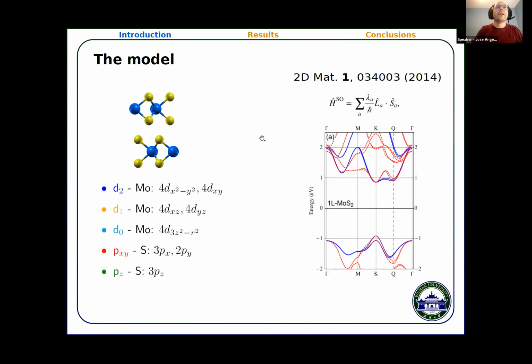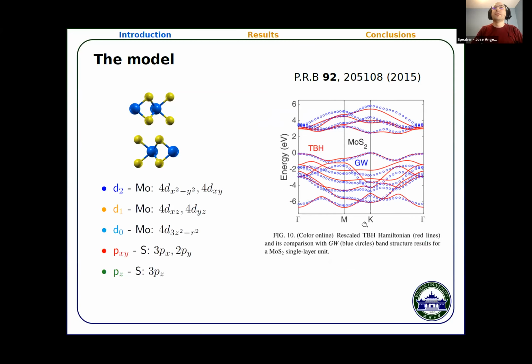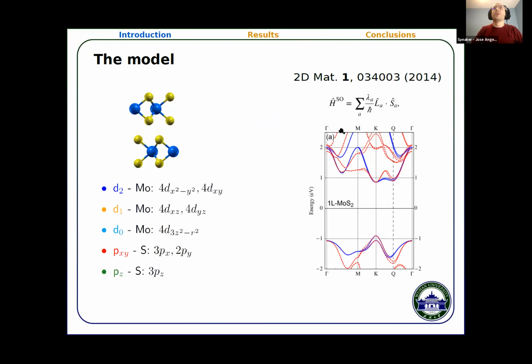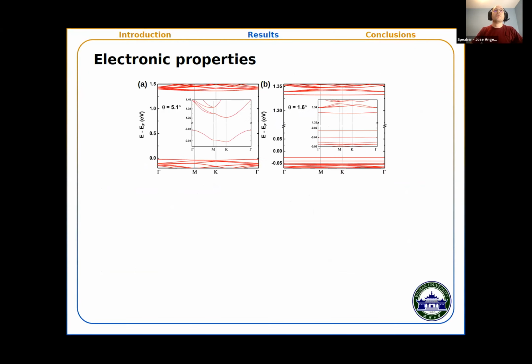So basically, we're using a tight binding model, and we use this 11 orbital model, and this fitting by the group of Kashiras. And we include in some of our calculations spin orbit coupling, since the atoms are quite heavy. So now we can plug our Hamiltonian in our homemade tight binding program, which is called TIPSY, and do, for example, normal diagonalization calculation.